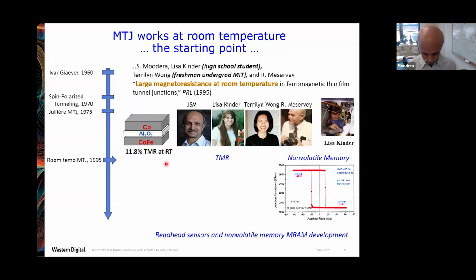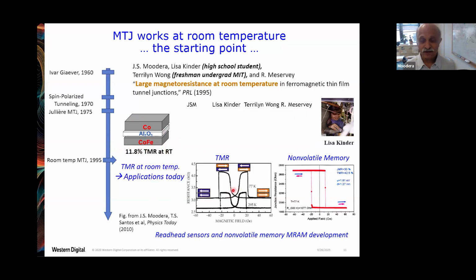And in fact, we were able to actually produce a very large TMR by carefully controlling the insulator thickness and also the cleanliness of the interfaces. This is done all in situ, one growth. So we were able to realize what was expected essentially 30 years ago or 20 years ago, what's called the TMR in between two magnetic electrodes.